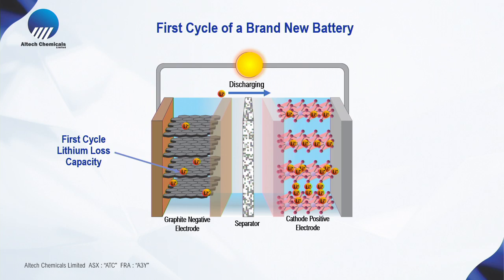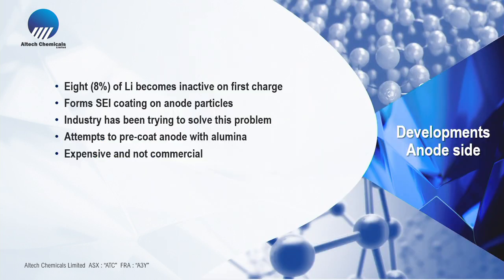Who knows about the first cycle lithium loss capacity? Well, the industry has been trying to resolve this because what happens with that lithium, it forms a layer around the graphite particle, which is called the SEI layer, or solid electrolyte interface. And when it forms this layer, the lithium becomes inactive. And so the industry has been trying to resolve this problem so that they can increase the capacity of the batteries, but currently, they've been trying to coat the graphite particles with alumina, but it's rather thick in layers, quite expensive, and not commercial.